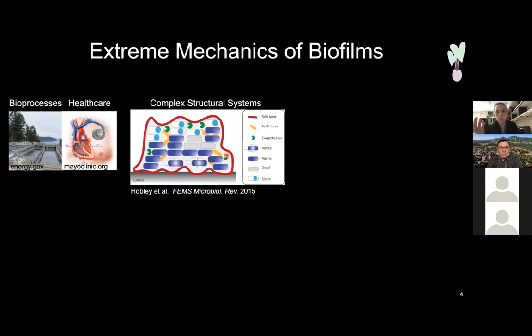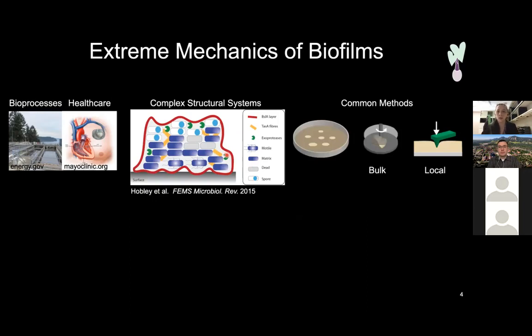One of the interesting things that has been looked at in terms of the mechanical properties is that they really only look either at the bulk or the local properties. One of the common methods is rheology, where they take these bacteria from a plate and group them all together. So you're losing that complex structure now, and they're just measuring the bulk system. This is really what Howard Stone's group does. So they're not able to capture how this hierarchical structure impacts the mechanics in those systems. And the other way that rheometry is used, they also grow the biofilms onto the rheometer, and that takes a little while, and then they measure those properties.